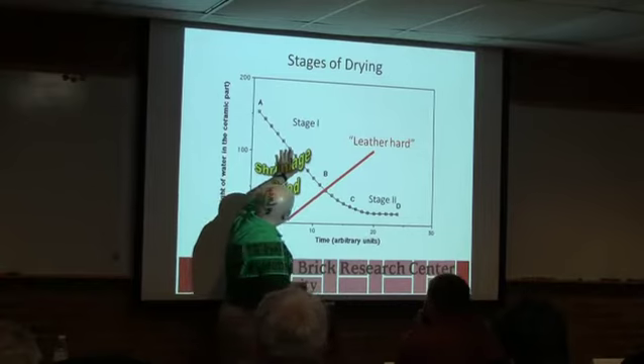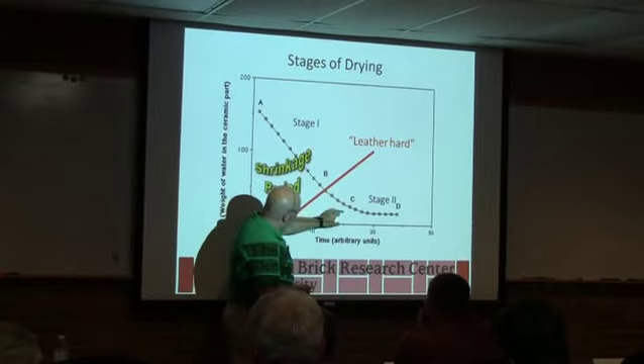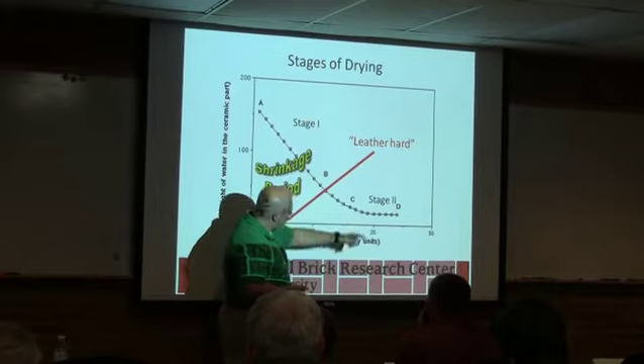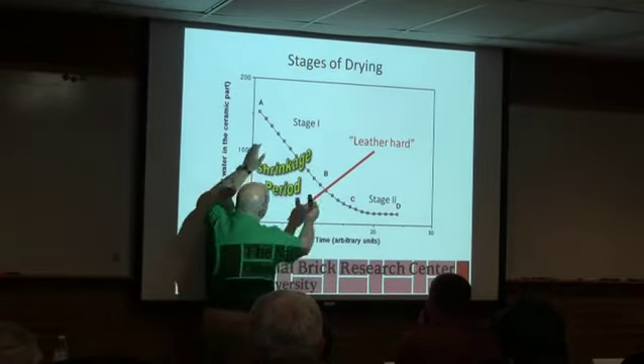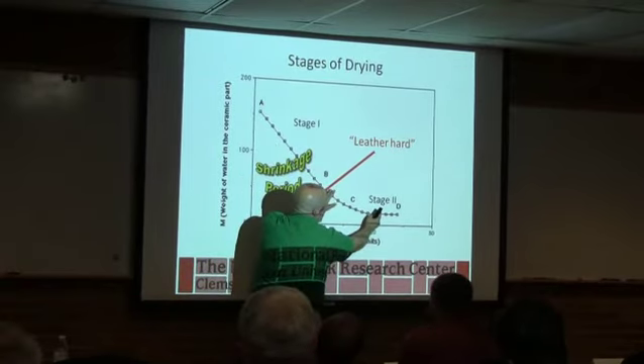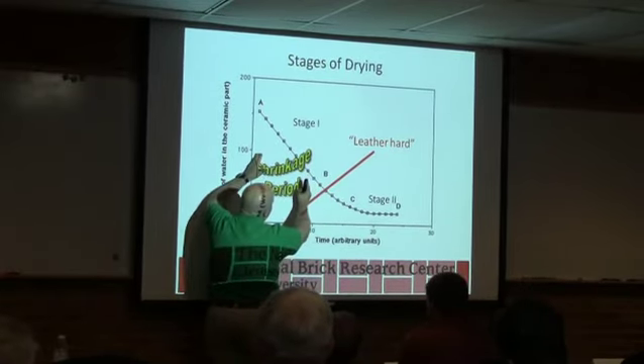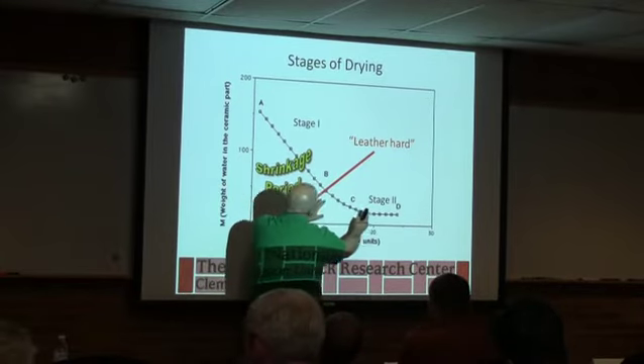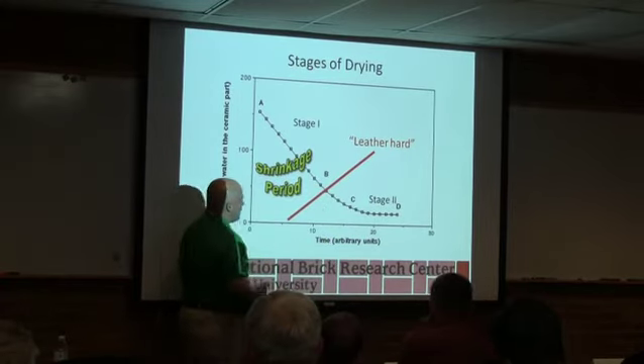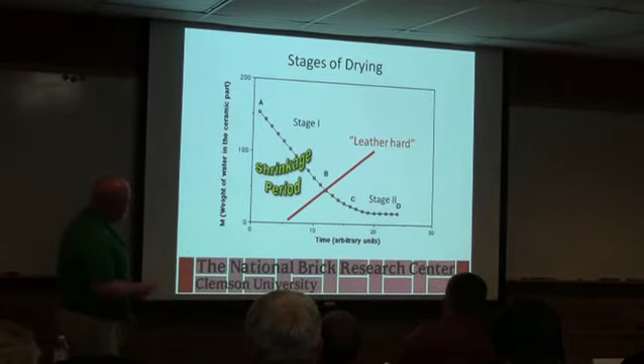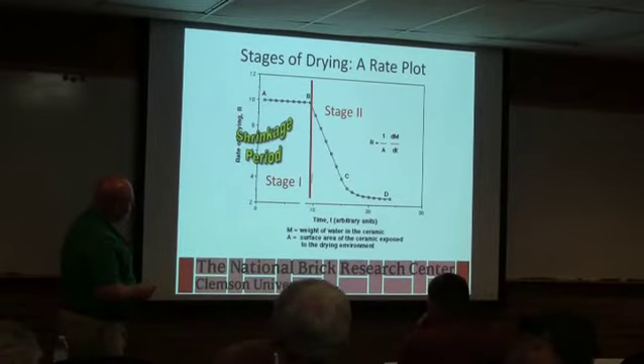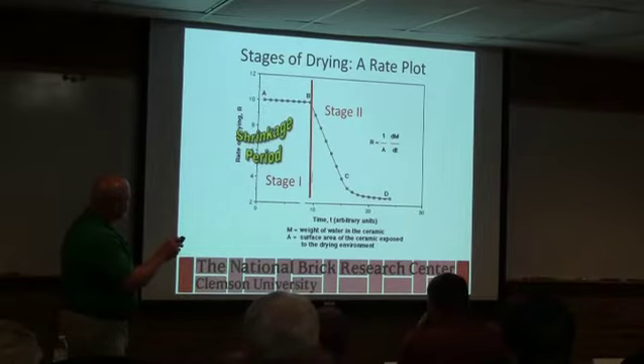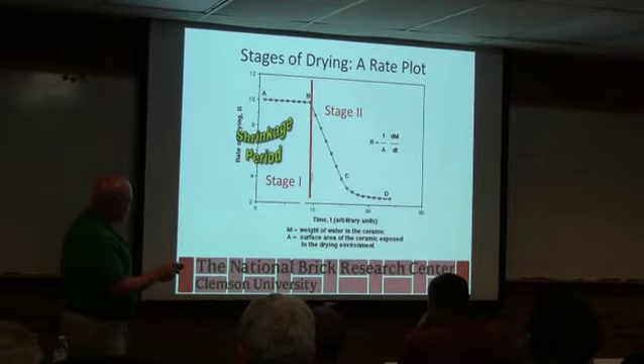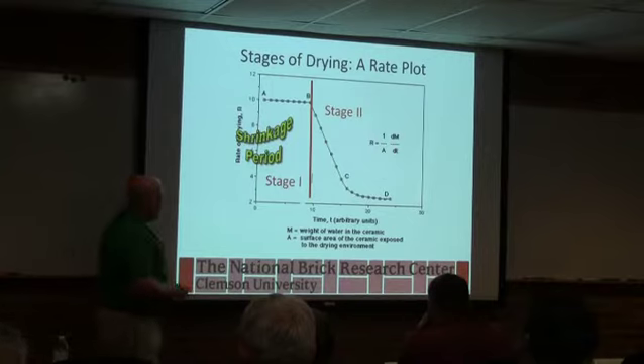So what's happening is that this is the forming water that's separating the particles. And when it is gone, we start to move into the pore water, and then we get into the capillary and the hygroscopic water as we go on. So the way we control this part of drying is different from the way we control this part of drying. Typically here we're trying to have very high humidity, low temperature, and as we move on, low humidity, high temperature to try to speed things up. So that's just the way we control the drying. You can plot it in different ways, but basically you see a very constant shrinkage rate in that first stage of drying, and then you see what they call a first declining rate period and a second declining rate period when you get into stage 2.